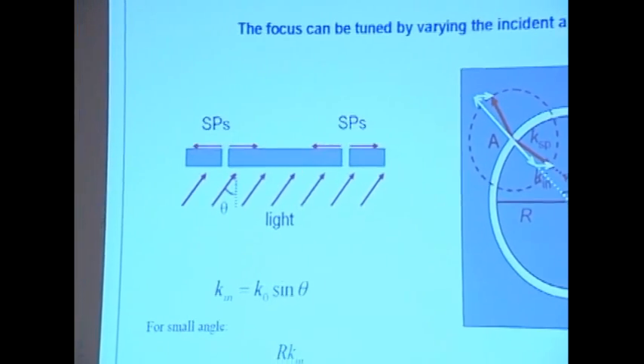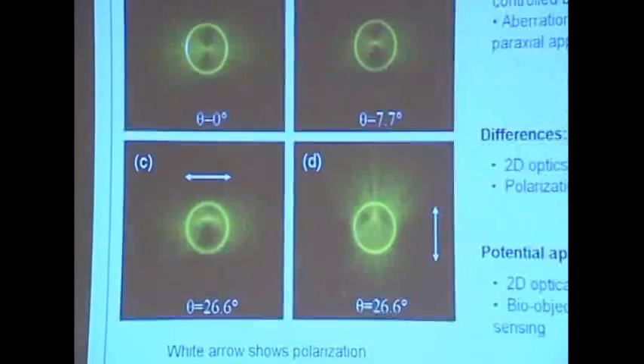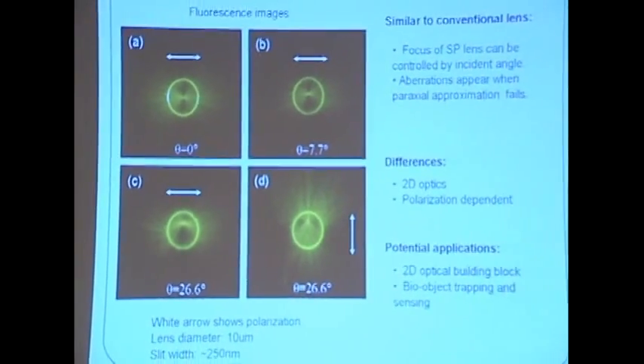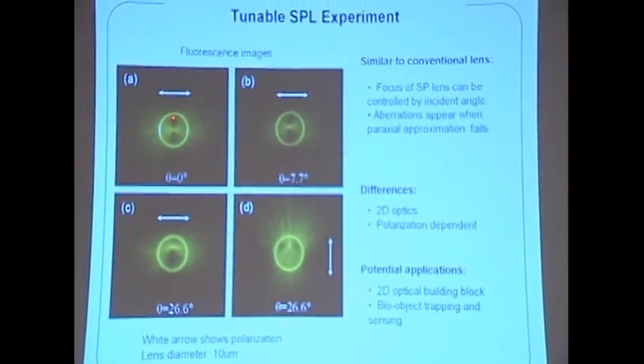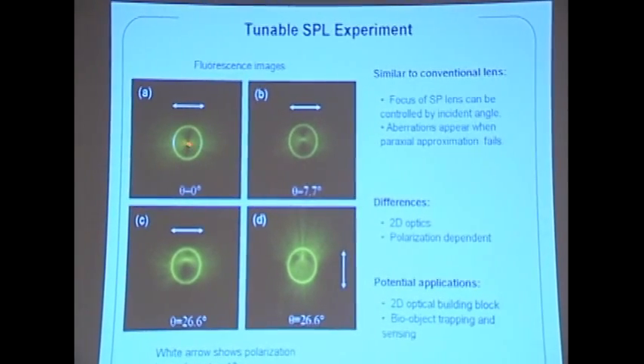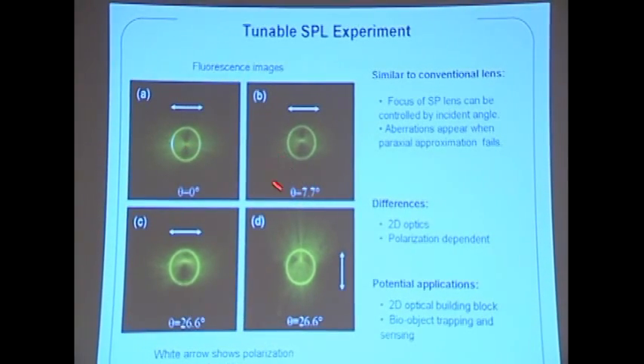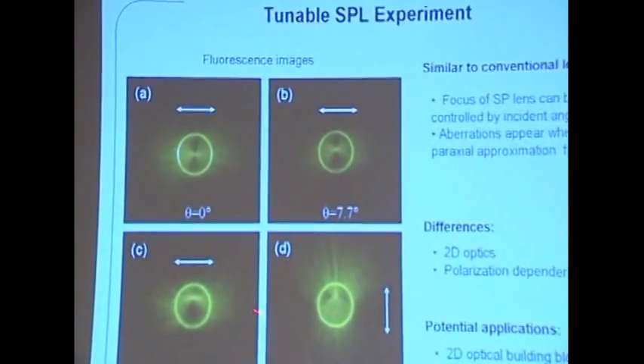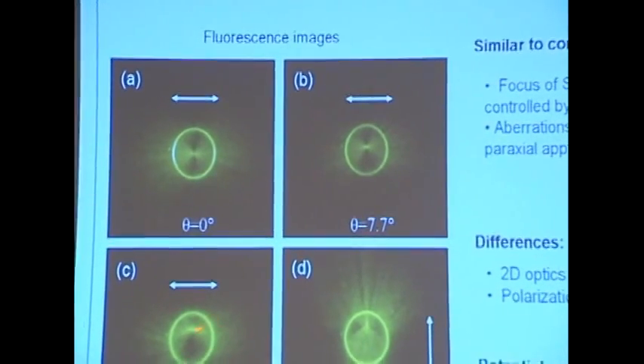And we developed a simple analytical theory to describe it. And this shows the experiment: with normal incidence, everything is focused at the center. And with 7 degrees, you can tune it upward a little bit. With 26 degrees, it's tuned even more.